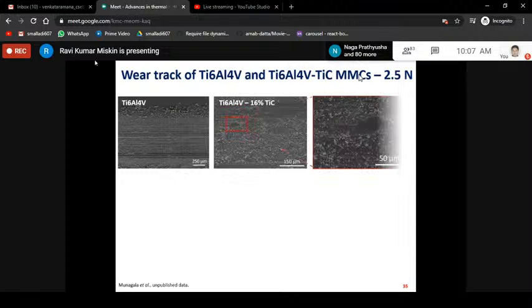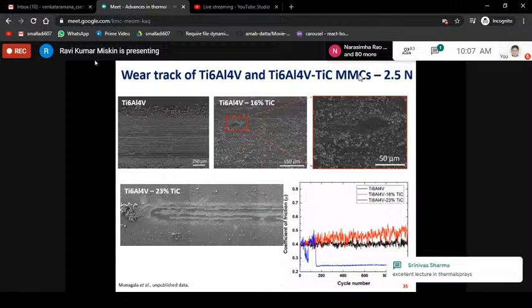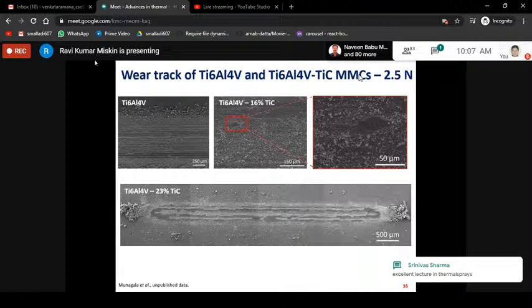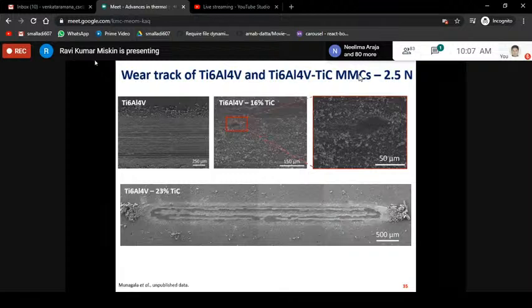Yeah. Even at 2.5 Newton, when we increase the normal load, we could see, one slide back. Yeah, thanks. When you see in case of titanium 64 and our composite with less carbide particles, you still have an abrasion process. That is the sliding marks you can see on the top images. So at 2.5, even if you have 16% titanium carbide, you're not seeing tribo layers. But when you come down to the bottom image, where you have 23% carbide, you could see there's a continuous strip that is formed. That's basically the wear track, which means that the ball that was sliding is not interacting with the subsurface. It's only interacting with those layers. That layer is like a protective layer on top, and the ball is moving on that. So that's why you don't see those friction rises. You see a drop in friction, and there's also carbon, which is further assisting its wear resistance.